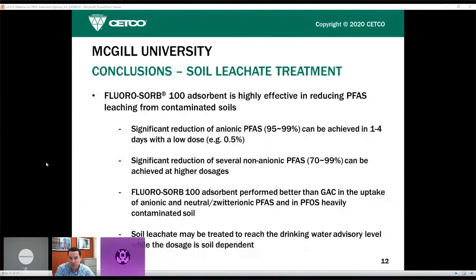So I want to summarize some of the results that they found. We can get significant reduction of PFAS in the range of 95 to 99% with as little as half a weight percent treatment of the soil. It works really well for ionic PFAS molecules, but for non-ionic PFAS compounds, it doesn't work as well. You get 70% to 99% removal, but if you want to treat those compounds, you simply have to add more of the media. Generally, we do better than GAC for most compounds, particularly PFOS. And what we found is that if you add enough FLUORO-SORB, you can treat the soil to reach the drinking water advisory levels on a leaching study. But it's soil dependent. If you have higher concentrations of PFAS in the soil, you may have to add more. Next slide, please.